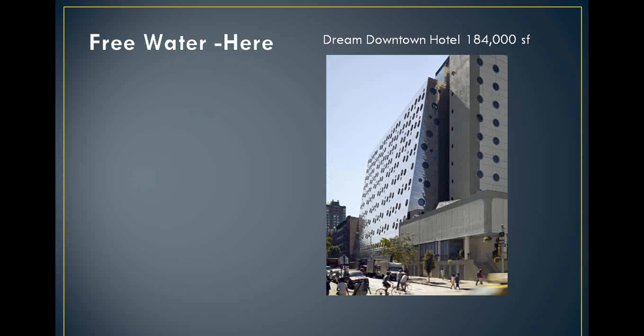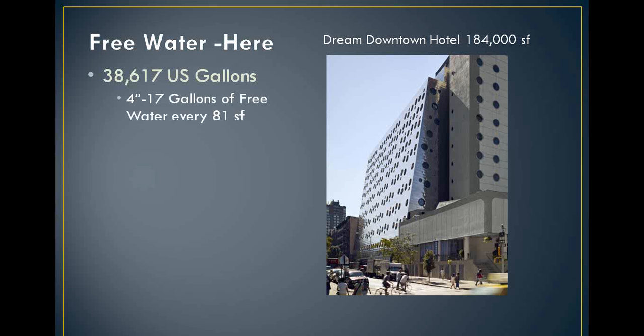I customize these presentations to each architectural firm that I go to, and this was one of their projects where I most recently gave this. It's a 184,000 square foot hotel, and inside there would have been 38,000 gallons of free water in the concrete slabs, waiting to come out into the occupied space. A cubic yard of concrete at 4 inches thick covers 81 square feet. So every 8 by 10 area you see at one point in time contained an extra 17 gallons of water.